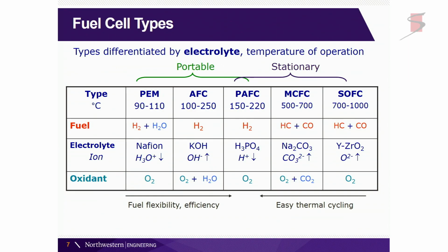And the two lower temperature systems, the one that is primarily used in automotive applications is the polymer electrolyte membrane, and you've heard of that also in the Nafion-based systems, which is often called a proton exchange membrane fuel cell, but in fact I would call it a hydronium ion exchange fuel cell. And then a little bit higher temperature is the alkali fuel cells that have been used very much, for example, in space applications. As you go to higher temperatures, you typically get increased fuel flexibility and efficiency. This is not an inherent thermodynamic efficiency from high temperature, but a catalytic efficiency, because catalysis generally proceeds more readily at high temperature, and so that provides you with that increase in efficiency.